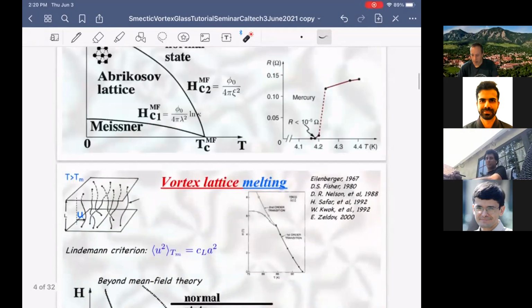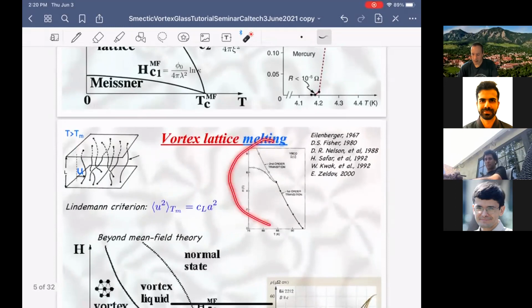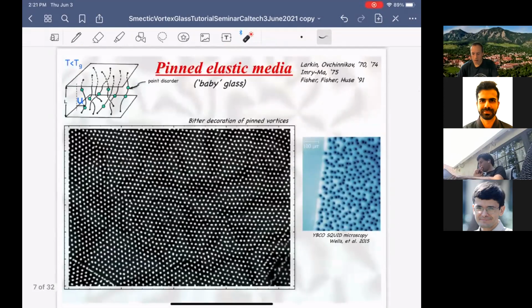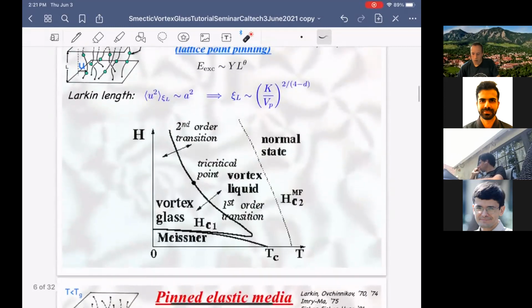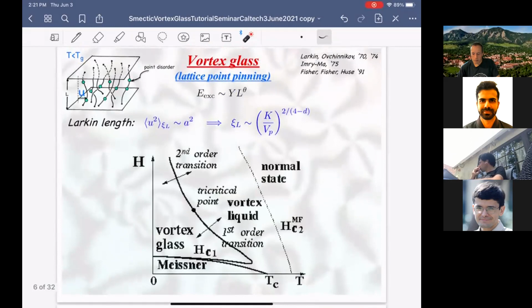And in fact, this is what I indicated here. Here's some data. So here's the tricritical point. Here's the first order transition. And here, what's seen by the SAFAR data is actually what seems to be a continuous transition. Okay, but what's the behavior of the resistivity drop? Can you quantify that using this theory? Yeah, so I will touch on that in a couple of slides.